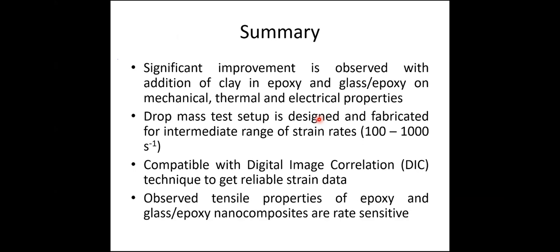So this is the summary of this phase 1. The drop mass setup was designed and fabricated for intermediate range of strain rates. It is compatible with digital image correlation to get strain data, and we observed that the tensile properties of epoxy and glass epoxy are very sensitive to strain rate. So this is the final outcome from the study.